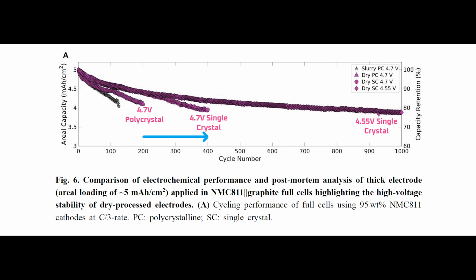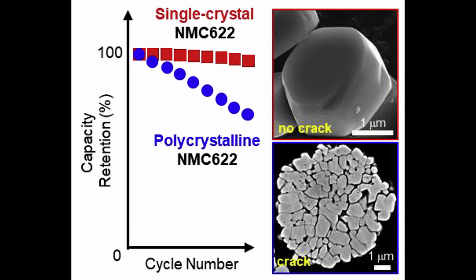Fifth, Zhang et al. used single crystal cathode to significantly increase the cycle life of their pouch cells. Single crystal cathode is more robust than typical polycrystal cathode material, but it's slightly more expensive. The combination of vapor-grown carbon fibers and single crystal cathode might add $5 per kilowatt-hour to the battery cost, roughly 5% more than a typical battery.